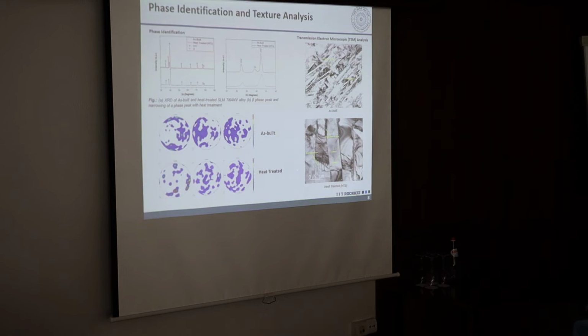Then we did phase identification and texture analysis of as-fabricated as well as heat-treated specimens. I'll just focus on this; this is the same region, and we have magnified it. A tiny strip of beta has been observed in the heat-treated case, whereas in the as-built case we don't have beta, or it is very low in fraction.